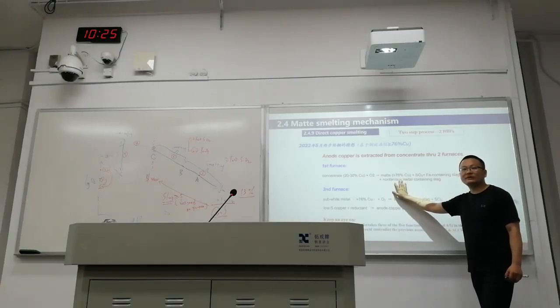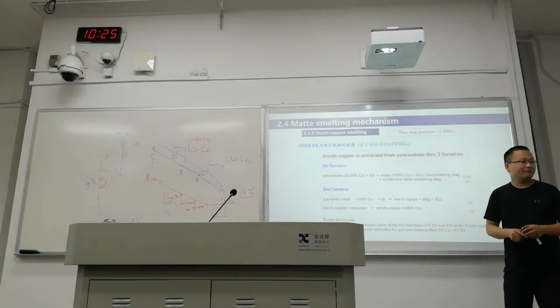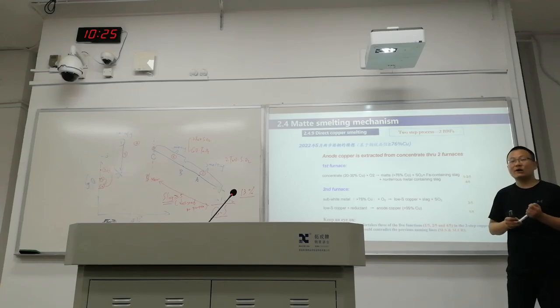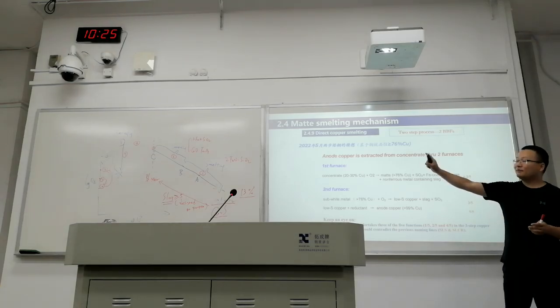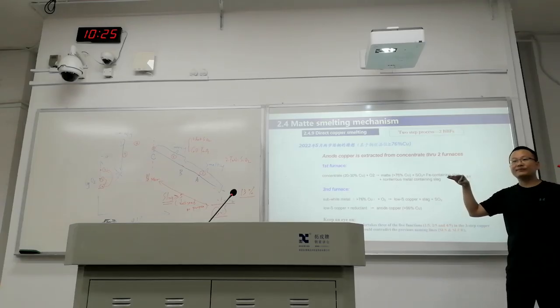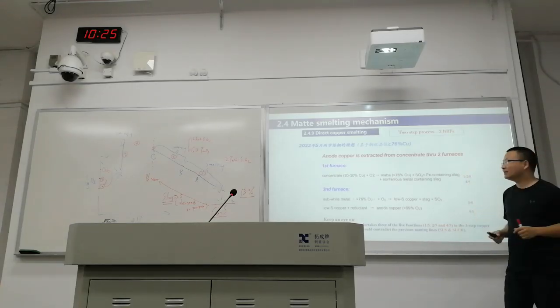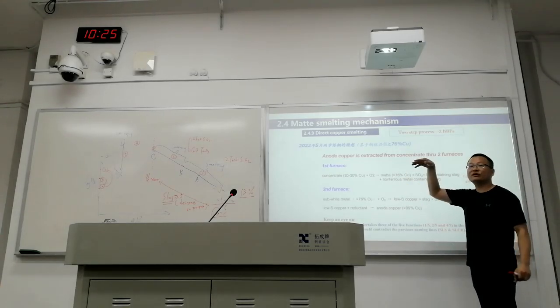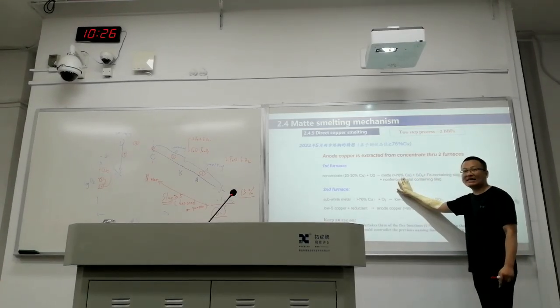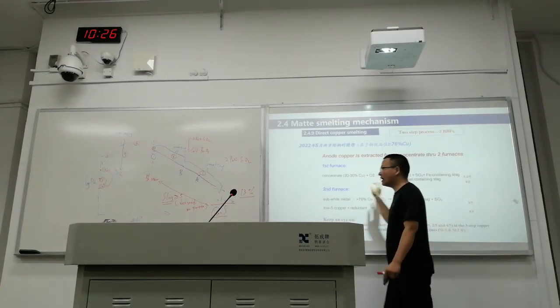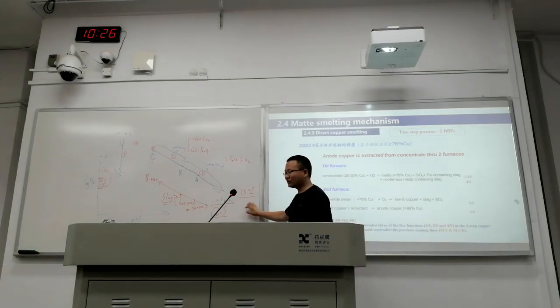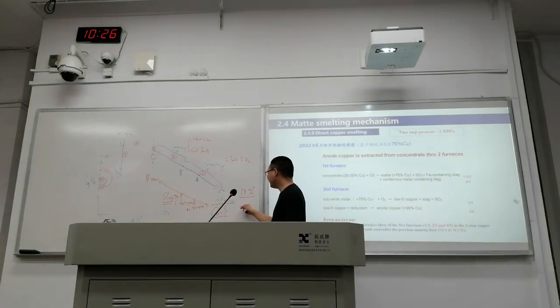Very close to white metal, and this one has already changed the concept from the phase diagram drawn by Professor Yazawa. In Yazawa's phase diagram, 70 actually is a limitation, the roof. And now we have broken the roof. We have arrived 76. Especially when you are having very low copper content, which means iron content will be very high. If this one drops, this one will increase, and you will have more serious problem of magnetite.